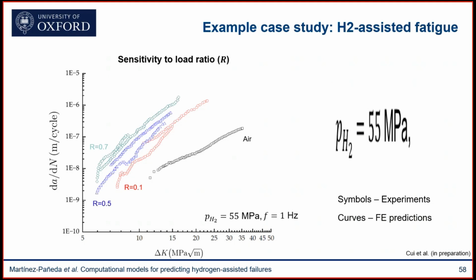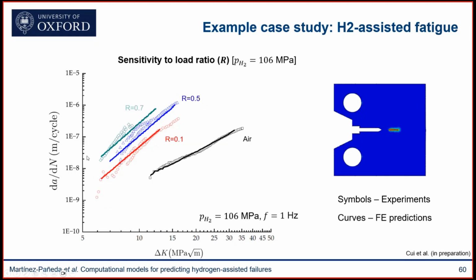And they have data for different loading ratios as well. You can see here for different loading ratios. So again, we take our model. We don't touch anything in our model. We just change the loading ratio. And again, we get a very good agreement all across the board for loading ratios of 0.1, 0.5, and 0.7.